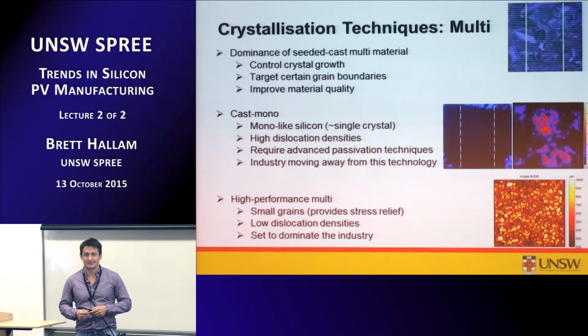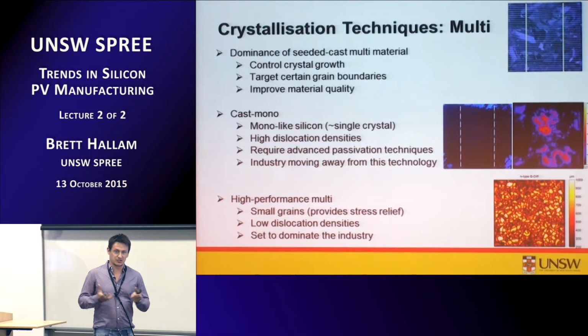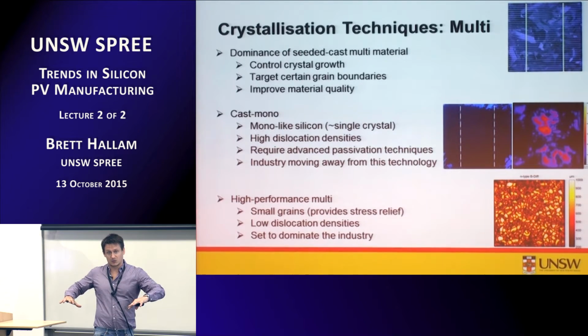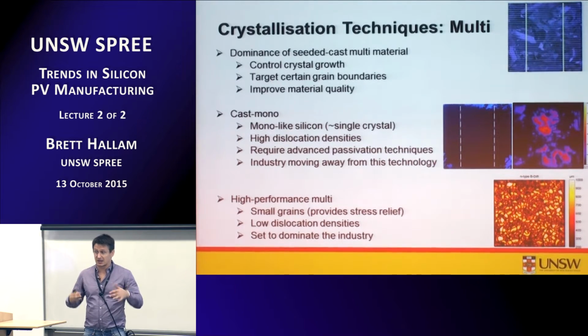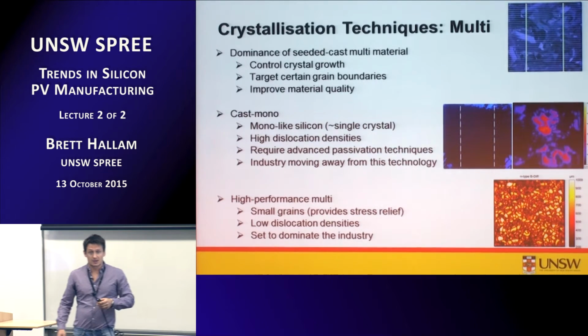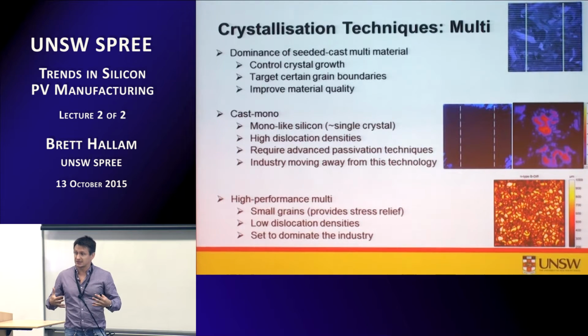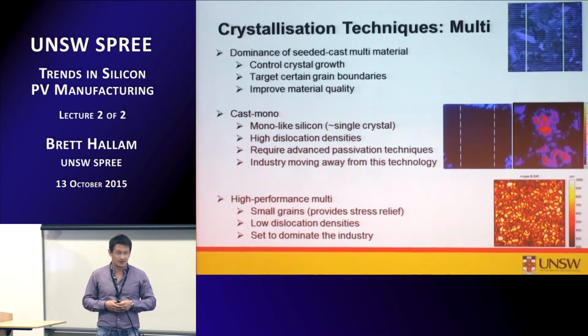Is that one big grain in the middle? Yeah. It's a seeded material, so during this casting process they take a monocrystalline silicon wafer or a chunk of silicon, and these cover the bottom of the cast. Then when they grow these, our cast, they heat up the silicon cast from the top, melts all the silicon, melts part of this seed, but they stop the heating process before you've dissolved all the seed. Then as you let it cool from the bottom up, it takes on the orientation of this seed at the bottom. So essentially you can grow monocrystalline silicon during a casting process.